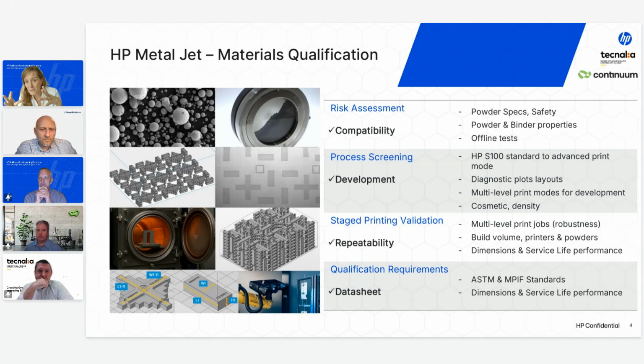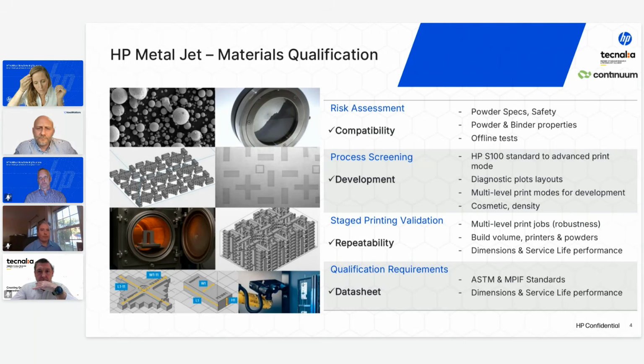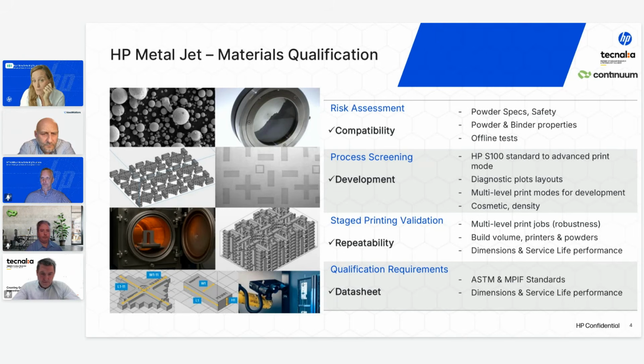And to complement these properties, we also focus on the microstructure of green and sintered parts. In this first stage, I can say that we focus on a very important checkpoint, which is building up what we call an analog press part or a green press part, that basically is a combination of a binder and a powder that we compress and later we sinter, which helps us to get an idea of how an analog part is going to behave, avoiding the impact of the layered form structure. And so we characterize here the green density, the green flexural strength, and if we sinter, the sinterability, alloy composition, and density, etc.